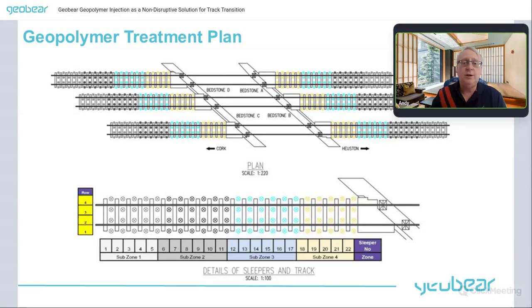So what you see on this bottom section here, we have zone 1, zone 2, zone 3, and zone 4. As you approach the bridge abutment, we inject more geopolymer into each zone to get a transition. So we want the soil to be stiffer very close to the bridge abutment and less stiff further away. So we varied the injection amount, the quantity, into each of the injection points as you approach the bridge. And for convenient reasons, we did that in 4 different sections. So we increased the mass of geopolymer injection in a steady and controlled manner in these different sections. Across each sleeper, there are 4 injections, and there's an injection in between each sleeper within the transition zone.